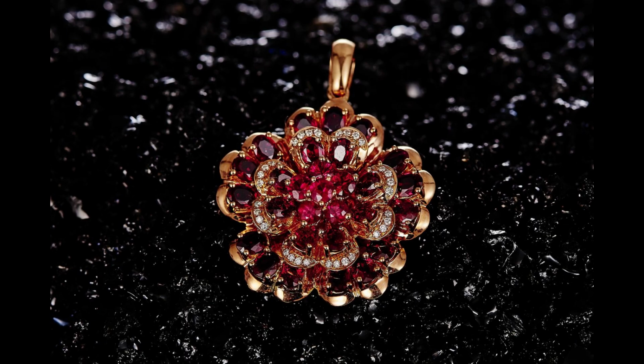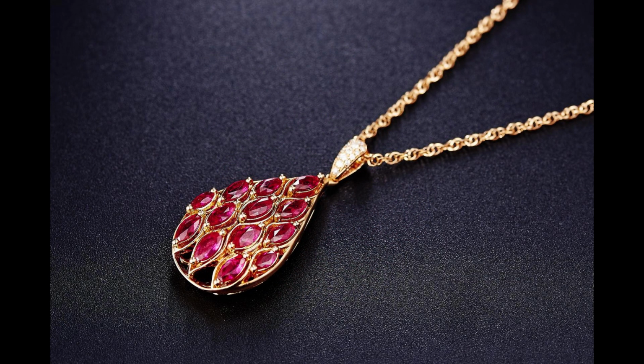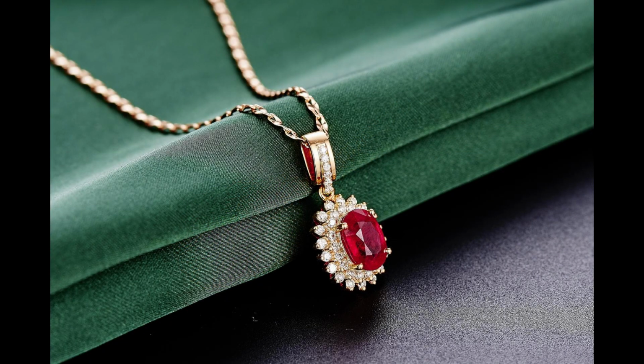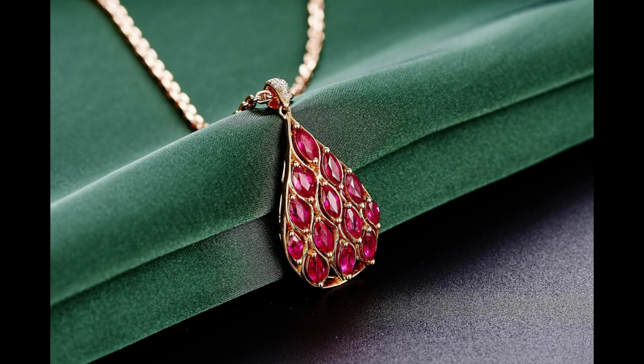In 1877, Frémy and Auguste Verneuil manufactured artificial ruby by fusing BaF2 and Al2O3 with a little chromium at red heat. In 1903, Verneuil announced he could produce synthetic rubies on a commercial scale using this flame fusion process, later also known as the Verneuil process. By 1910, Verneuil's laboratory had expanded into a 30-furnace production facility, with annual gemstone production having reached 1,000 kilograms, 2,000 pounds. In 1907, other processes by which synthetic rubies can be produced were developed, namely Czochralski's pulling process, the flux process, and the hydrothermal process. Most synthetic rubies originate from flame fusion due to the low costs involved.